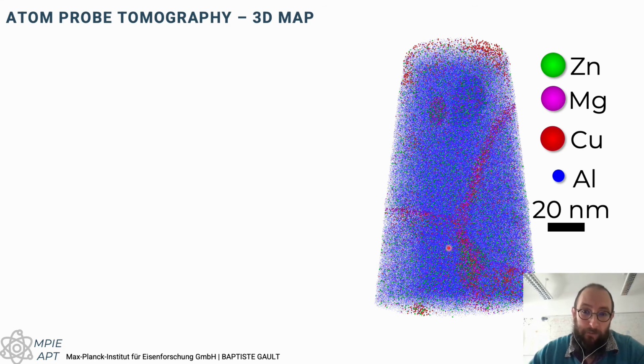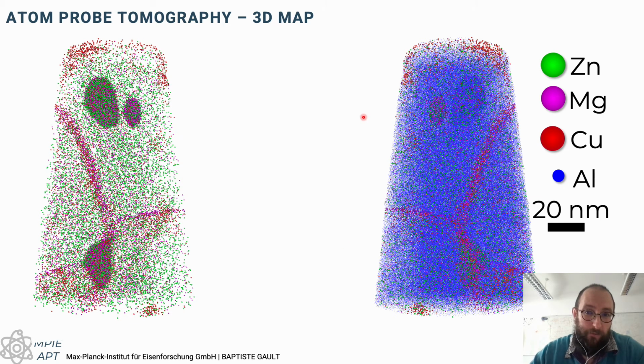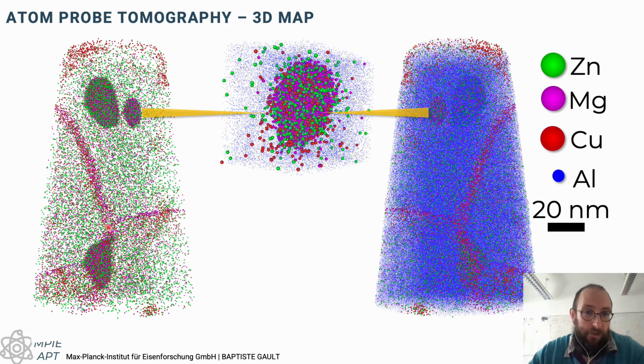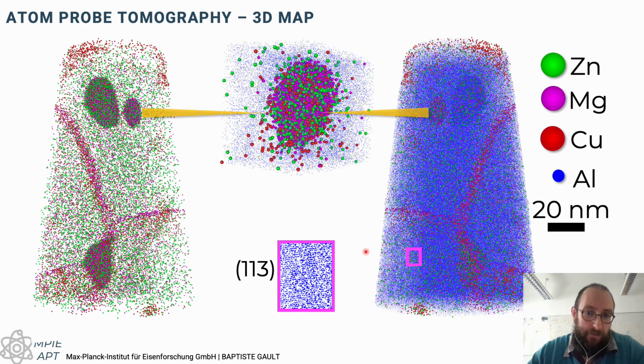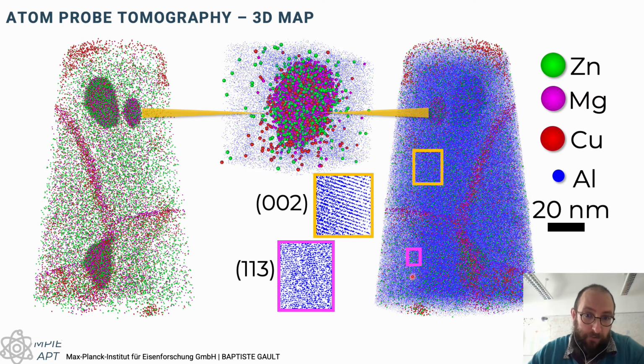So we can see now, for example, in this nanocrystalline aluminium alloy, there's 3 grains that have been analyzed. We can rotate the volume in 3 dimensions. We can look and probe the composition of the particles that we have here, the precipitates that are inside of the grains, and the composition, for example, here of these grain boundaries. We can isolate individual particles to look at their individual composition. And sometimes we actually can find trace of the crystallography of these different grains. So here we can image different sets of atomic planes within the reconstruction.